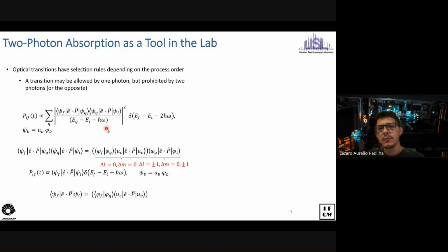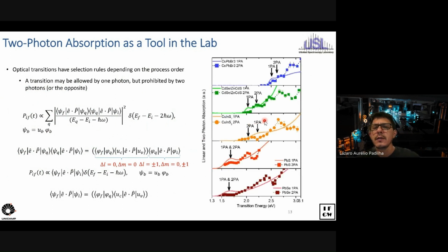Here, I just showed you a brief example comparing perovskite nanomaterials, where you have the first one-photon absorption here and the first two-photon absorption right there. For cadmium selenide, this is even clearer: you have the one-photon absorption here and the first two-photon absorption peak right there. This occurs because of the difference in parity symmetry for one- and two-photon absorption, so that two-photon absorption mostly occurs at higher energy than one-photon absorption. For CIS, this is inverted. You have a first weak two-photon absorption peak here below the one-photon absorption peak.